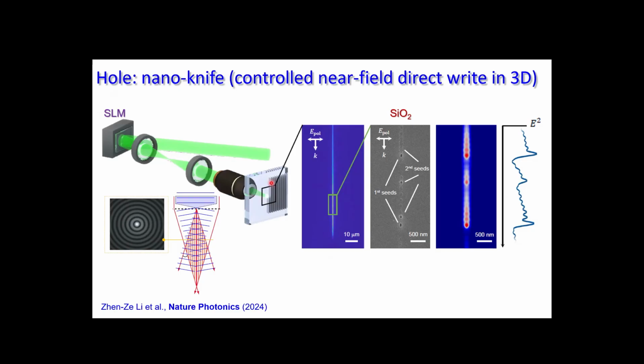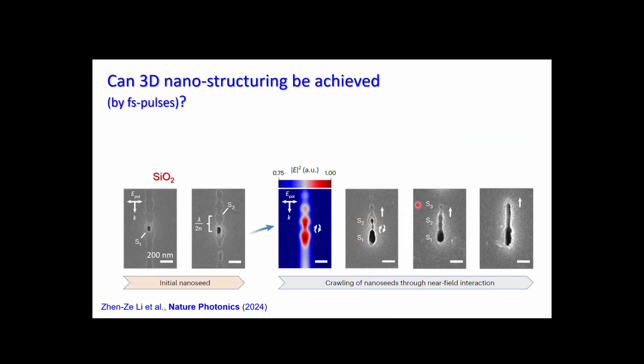So this pattern was recorded in transparent materials and then investigated. For investigation and final application, wet etching was used. It's slightly different for different materials, but usually it's quite aggressive HF etching, hydrofluoric acid. But this also reveals what the modification inside is. And what we see is that along the propagation of our beam, we see some strange pattern, which is a little bit chaotic. At the same time, if we look into more detail and try to understand how it is evolving: light propagates from the top, it's a very long Bessel beam, and suddenly in some places we see that definitely silica was modified, and that's why it was etched out.